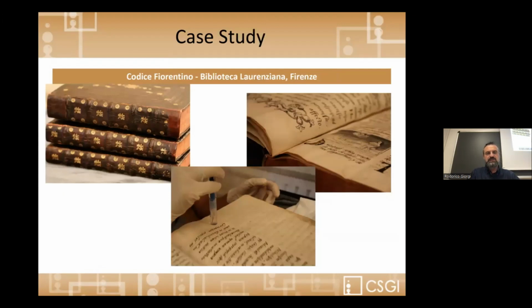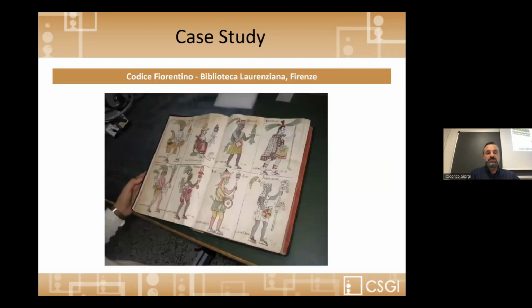And then we used these methods also for the deacidification of the Codice Fiorentino, which is conserved at the Laurenziana Library in Florence. This comes from colonial time in Mexico, in Tenochtitlan, and was realized by native people with friars living in Tenochtitlan. Iron gall ink was used, and we had acidic conditions of the paper and also, unfortunately, some ink corrosion issues. But we also have roughly 3,000 drawings made of dyes and colorants coming from the painting tradition in Mesoamerica. So it was very important to work with something compatible with these materials, which are really sensitive also to pH variation and obviously to the effect of solvents.